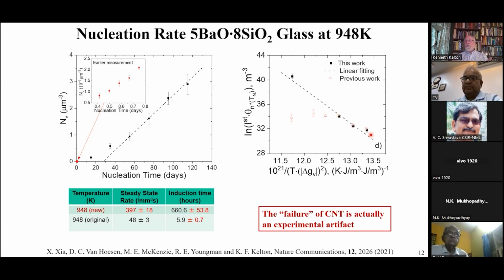And this is extremely important to the silicate glass community. As I mentioned, they need to know these nucleation rates and these induction times very accurately to develop controlled microstructures for glass ceramics. This experiment indicates that probably every existing experiment in silicate glasses for low temperatures is wrong. So they need to go back and re-examine this. But the classical theory didn't fail. People are always trying to find places where the classical theory failed.